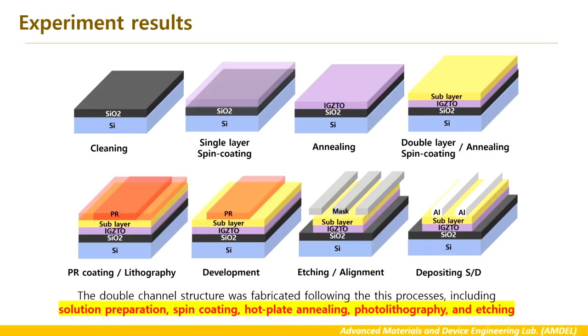The fabrication process for the double layer structure involved several steps. First, solution preparation and spin coating, followed by hot plate annealing. Then we used photolithography and etching to define the device pattern. This step-by-step process allows us to systematically study the effects of different materials and structures.